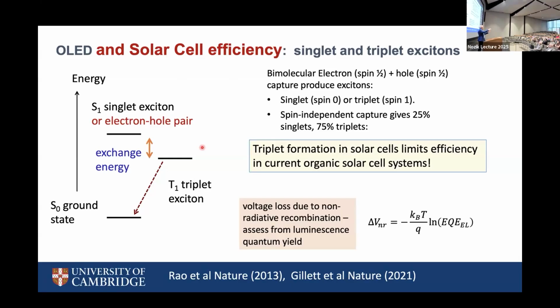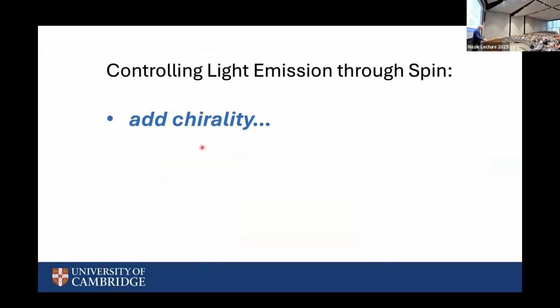They could have been injected from the two electrodes when LED. Electrons and holes, through the dynamic equilibrium, they will recombine and then reseparate. That's how solar cells should work. But the recombination can form triplets, and it's something we've studied over the years. They really do form, even in these 20% efficient cells. And finding ways to get rid of those triplets is going to be very important. So that's a sort of quick run through about 3 decades of efforts with the organics.